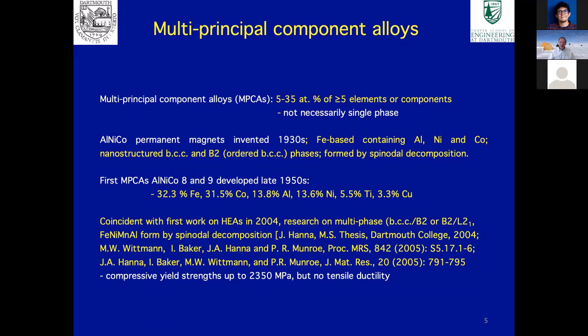And the first multiple principal component alloys were really alnico alloys. Alnicos were invented in the 1930s. Although it sounds like they're an iron nickel cobalt alloy, they're really an iron-based alloy with those elements in. And they consist of B2 and BCC phases. B2 is ordered body-centered cubic. And in the 1950s, Alnico 8 and Alnico 9 were invented. And if you look at the compositions, they were clearly multiple principal component alloys. So they've been around for a long time.